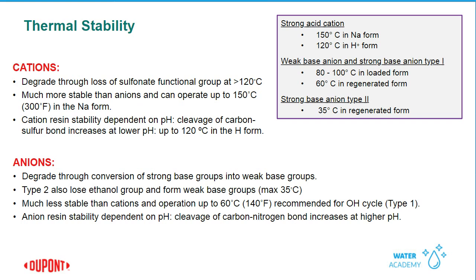The same for the ions that are in the water that we try to capture with the resin. So let's take sodium as an example. Sodium is not only there as Na+, it's there as Na+ surrounded with water. And sodium is less hydrated, has less water molecules around it. So when it's captured by the resin, the hydrogen will be placed to the water and the sodium is bound by the resin. That means that the hydrogen takes more water out than the sodium is bringing inside the resin bead. With that, we lower the amount of water in the resin, and because of that, the resin will shrink.